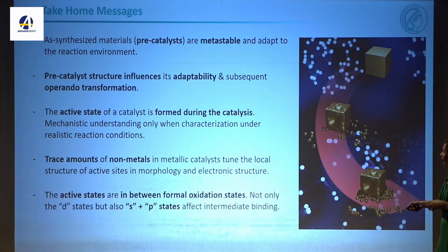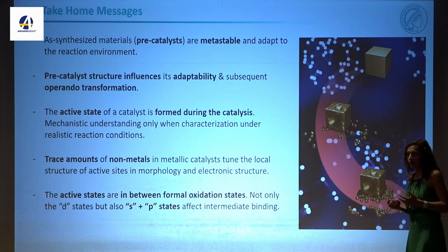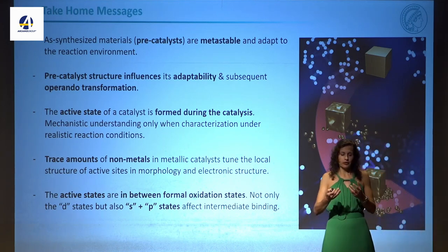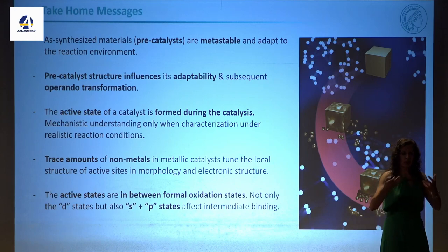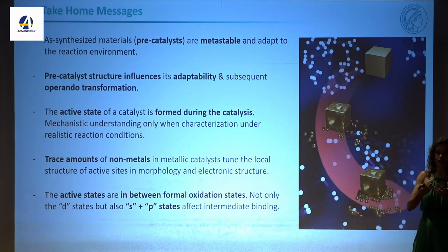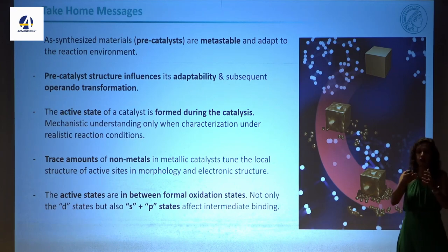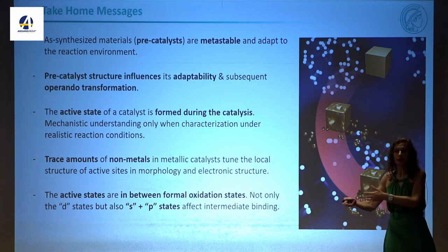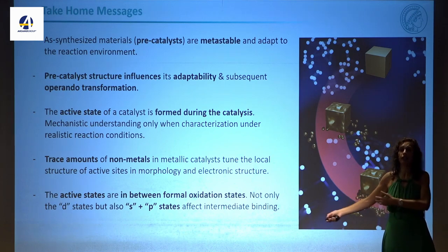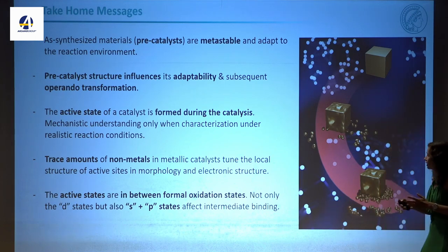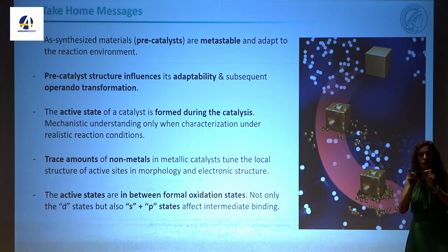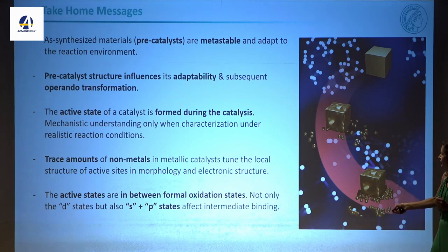The active states are in between formal oxidation states. In many cases in catalysis, you think that what you need is not the most stable material. What is doing the catalysis is what we call the frustrated phase transition. We start with a pre-catalyst, and we want something that doesn't convert completely to the most thermodynamic state, because that will be the dead, deactivated state. So frustrated phase transitions, in this case, in between formal oxidation states. I showed you from some of our data that it's not only the states that matter, but the states will also affect the intermediate binding.